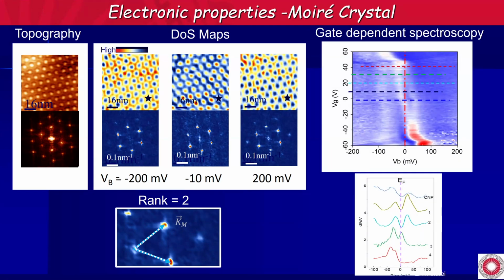When we look at the gate-dependent spectroscopy, you see a flat band here. When the Fermi energy is in the flat band, you open a gap here, and you can see this more precisely here. When the Fermi energy is outside of the band, it's narrow, and it broadens when you bring it into the band. All the beautiful things that we saw on just twisted bilayer graphene without being aligned to boron nitride. And of course, because we have many different angles, the region over which you actually have this flat band will depend on the twist angle, because we have a whole new family of aligned crystal.